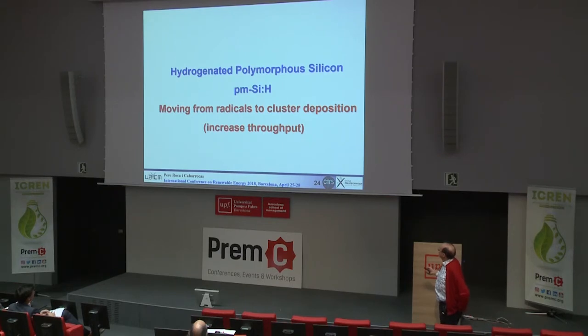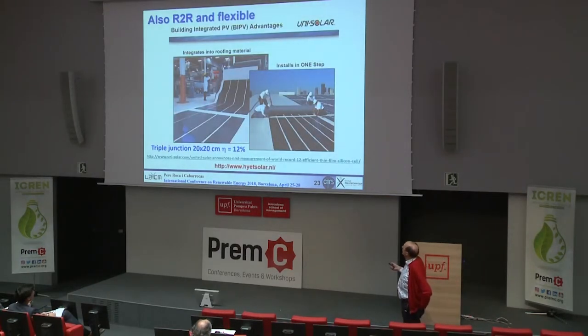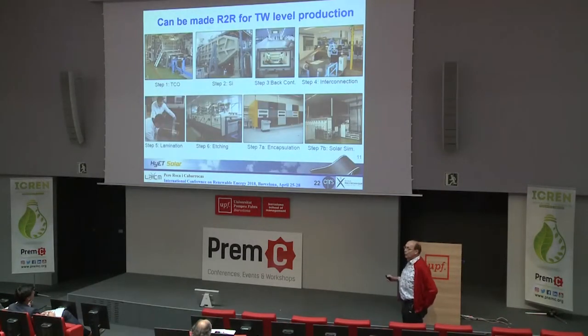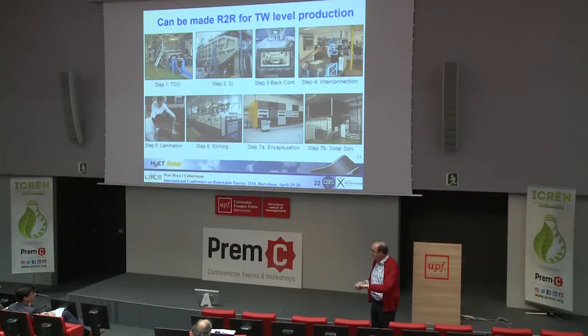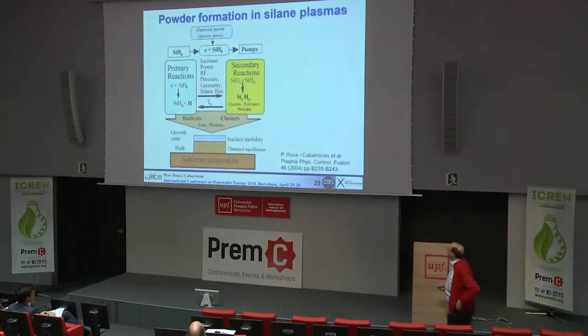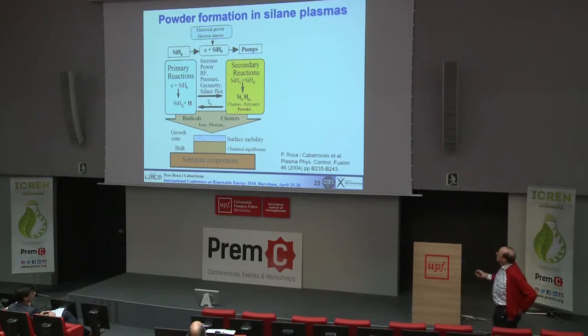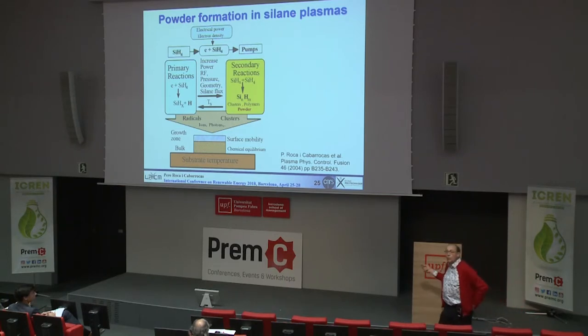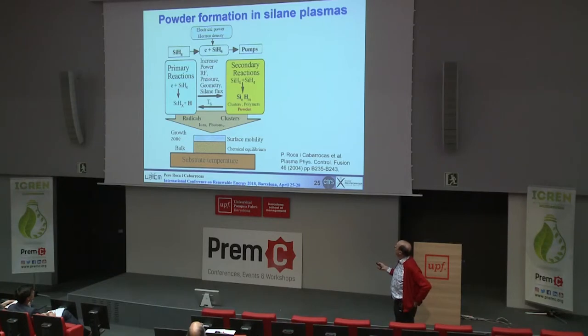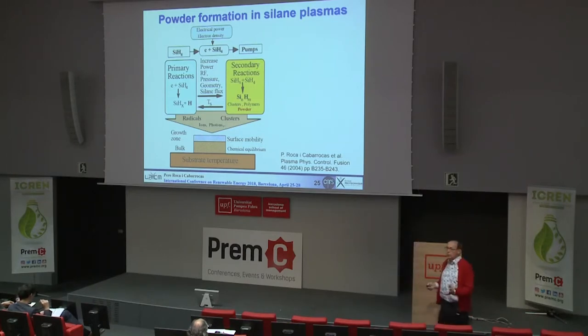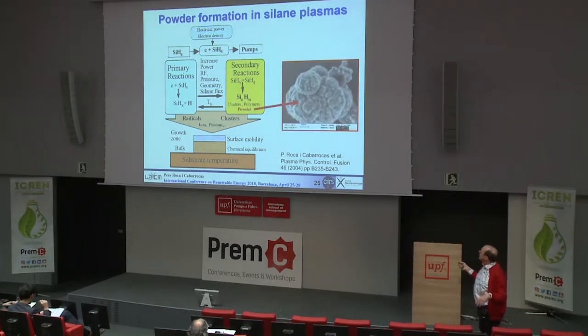If we want to get more production out of these reactors, we need to increase the deposition rate. And to increase the deposition rate, it's easy. Well, you have a plasma CVD reactor, you put silane, you put power, and if you want to go faster, you put more power. You increase the power in the system, or the pressure, or the gases, and then you have higher growth rate, but you also have gas phase reactions. So you have problems, you can make powder.